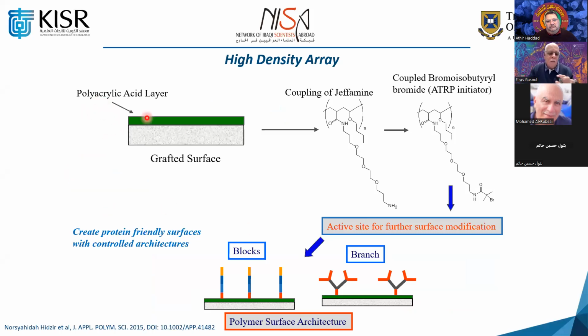What did we do? Here, for example, I'm giving you an example of a polypropylene surface, and we grafted a polyacrylic acid layer on top of it, but actually we used vinyl ether as well. So it's a copolymer of both of them. And then we reacted that, coupled with Jeffamine, in order to introduce that amino group onto the polyacrylic acid.